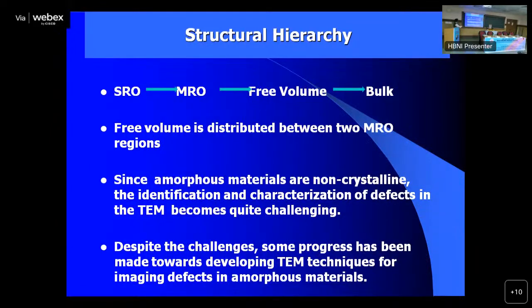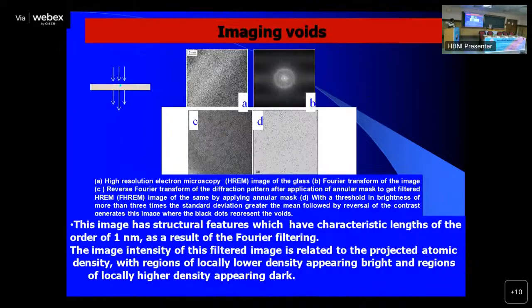So we have done these two. Now we have the free volume or the open space, which needs to be determined. And once you have determined this, the bulk structure is known for the first time for any glass. Okay? So we did that again by microscopy using a new technique, which is known as filtered high resolution electron microscopy.